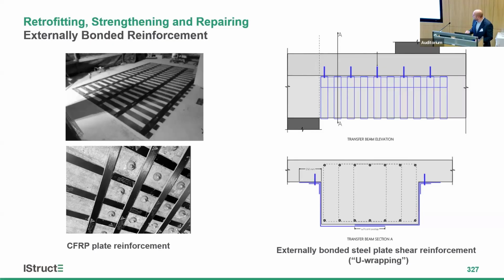The one with the bolts was where the drilling couldn't be guaranteed to not miss the reinforcement, so the carbon fiber is basically substituting reinforcement that might be damaged during drilling to install through bolts. The indicative example on the right is a U-wrapping of a steel plate to increase the shear capacity of the beam. For both steel plates and CFRP,